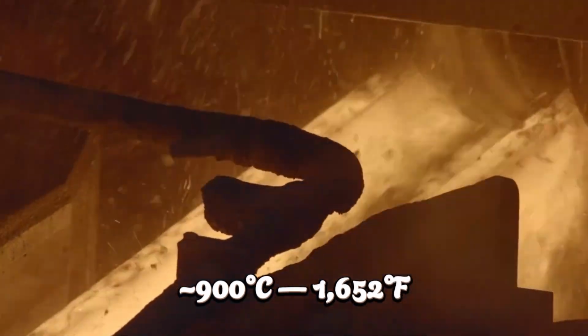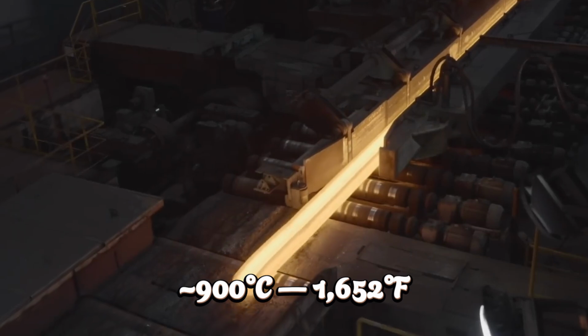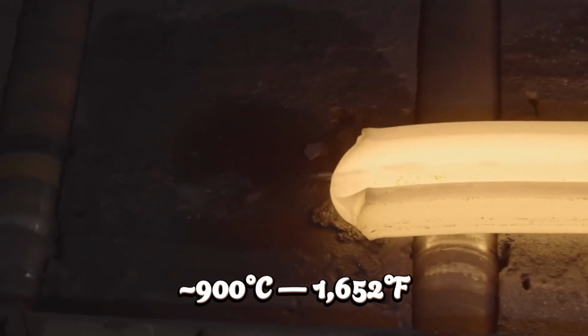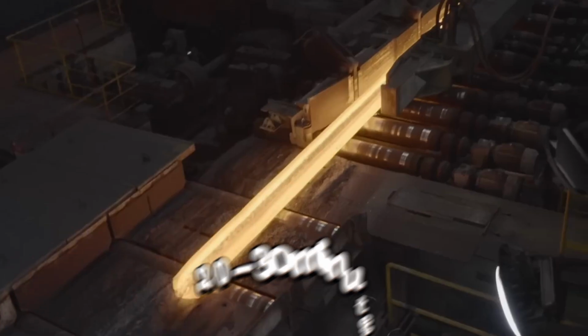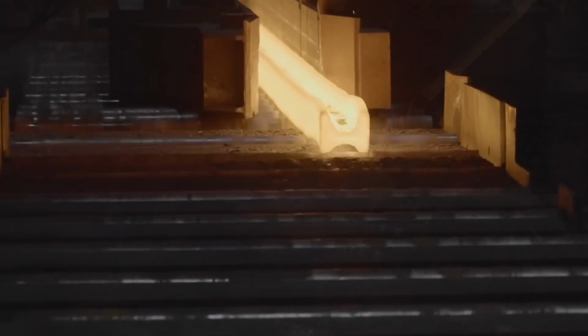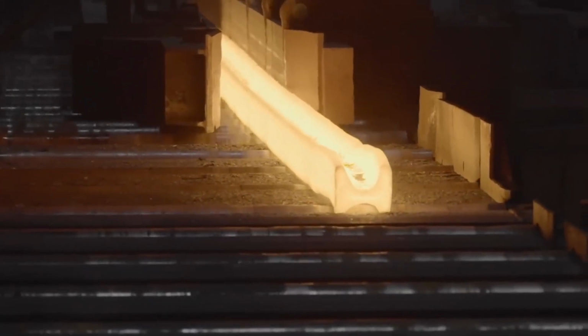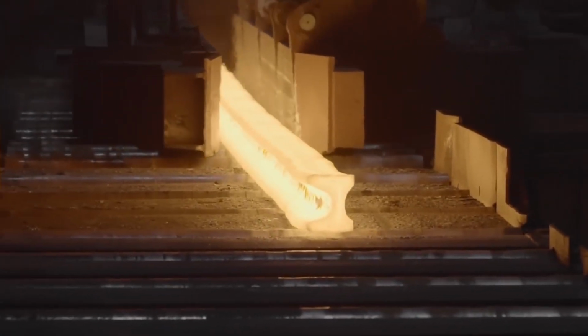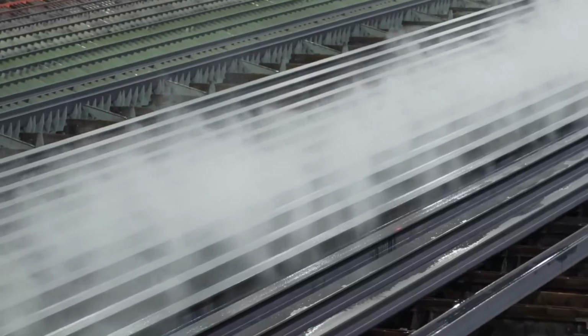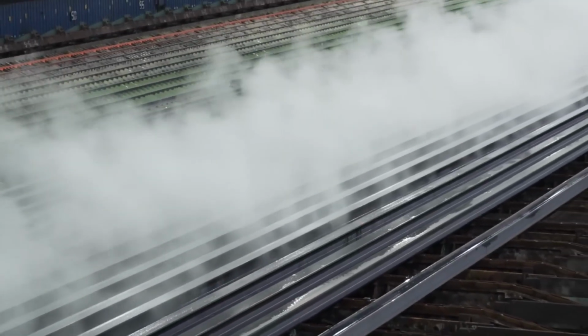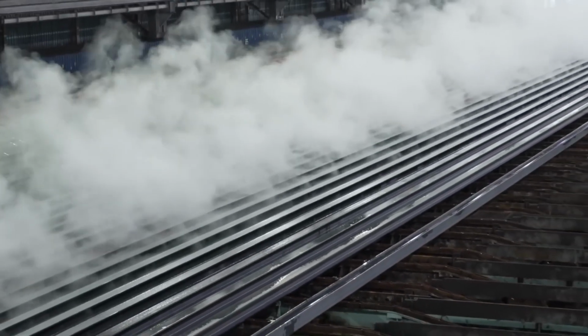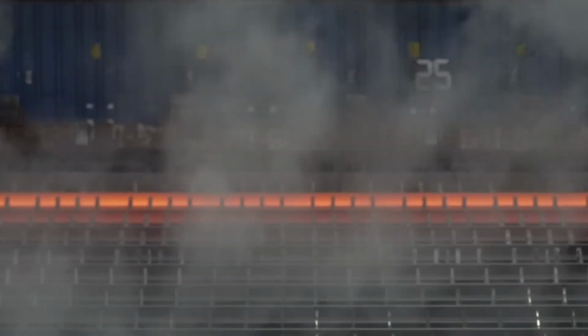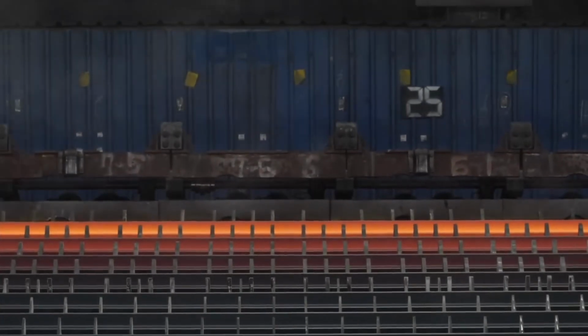Beams cool from approximately 900 degrees Celsius, 1,652 degrees Fahrenheit, down to ambient over 20 to 30 minutes. Cooling must remain symmetric. If cooling rate varies across flanges, beams twist by several millimeters. Roller lifts move beams sideways to balance exposure. Thermal cameras monitor cooling uniformity across length and flanges.